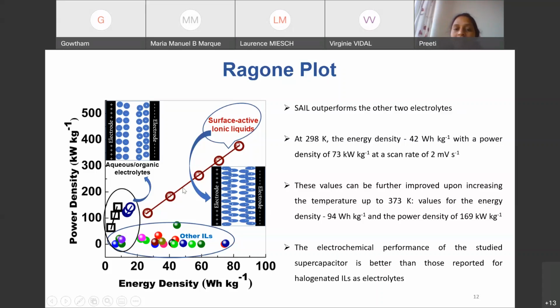But when we consider the neat surface active ionic liquid with increasing temperature, we are increasing both energy density and power density. And that's a very interesting phenomenon. This might happen because the orientation of the surface active ionic liquid on the electrode surface is different as compared to the aqueous or organic electrolytes or other ionic liquids, which are not able to form the nanostructure on the electrode surface.